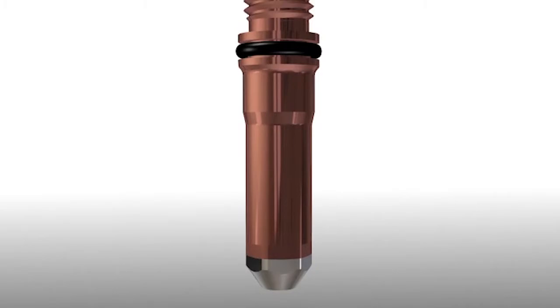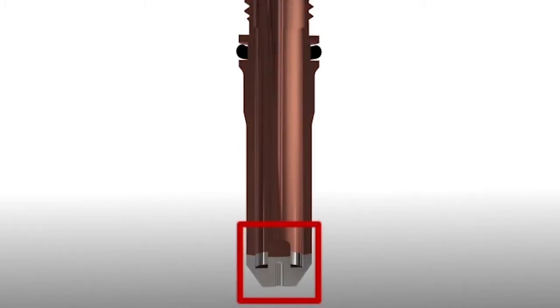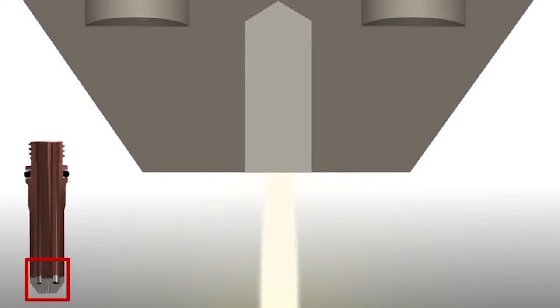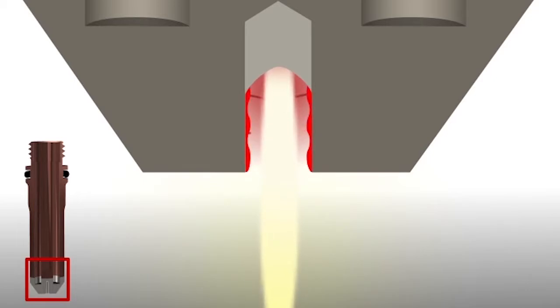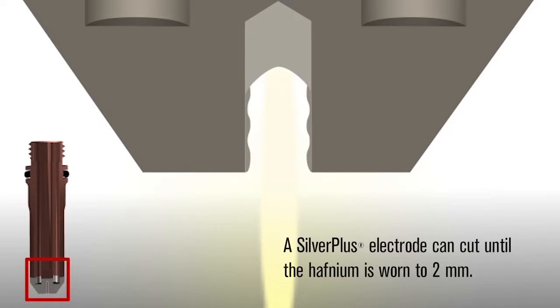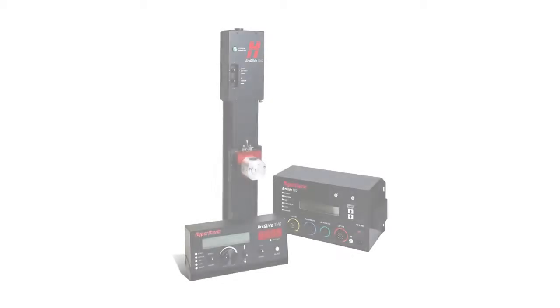With silver electrodes, a layer of silver oxide forms on the walls of the electrode as the hafnium wears. Unlike hafnium oxide, silver oxide works to remove heat from the electrode, preventing overheating and premature failure. Additionally, hafnium wets the silver much more effectively than it wets copper, providing a stronger physical bond between the hafnium and the electrode body. While a copper electrode is fully worn at 1 millimeter, a silver electrode can cut until the hafnium is worn to 2 millimeters while still maintaining good cut quality.